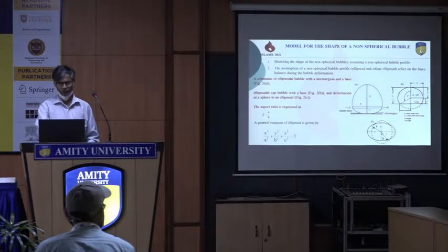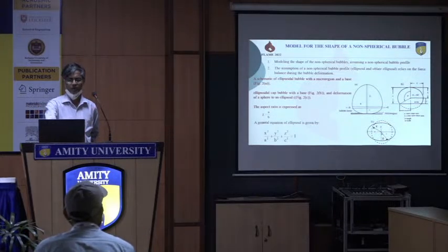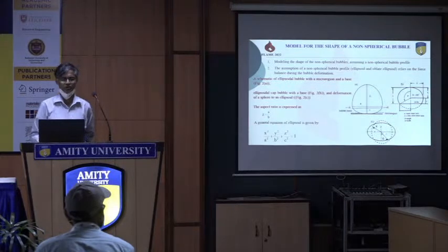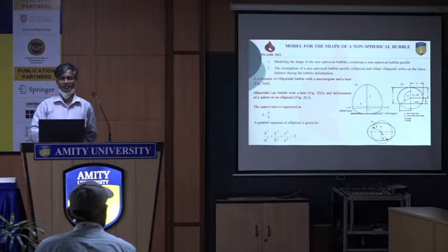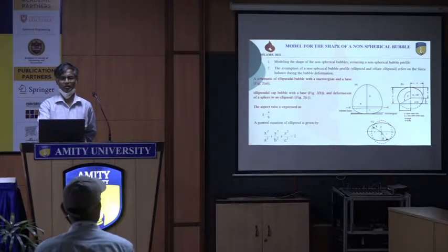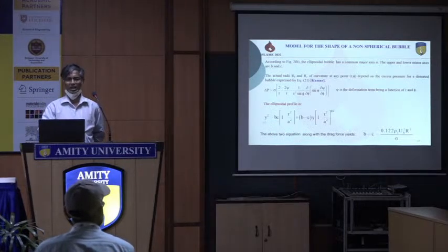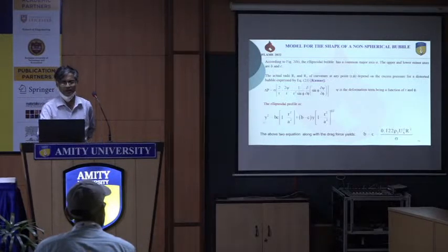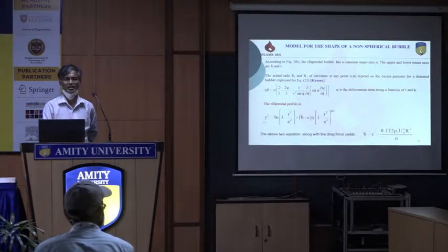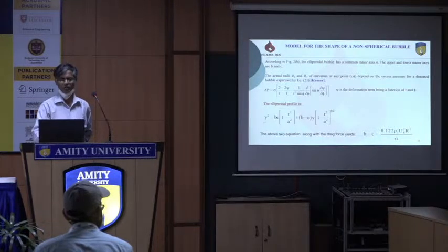At the same time, we have considered a bubble profile to find the bubble shape. We picked an ellipsoidal bubble profile. Then we find the aspect ratio, which is basically the major axis by the minor axis. We put this aspect ratio in the capillary deformation equation, where psi is the deformation term. This ellipsoidal profile and this force balance equation, in terms of polar coordinates, have been solved simultaneously.